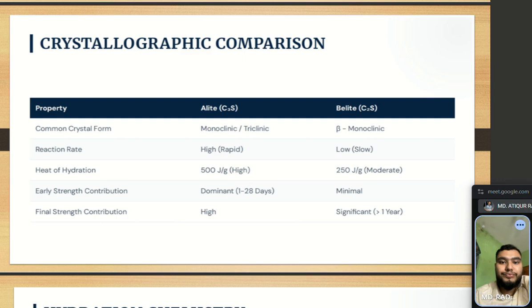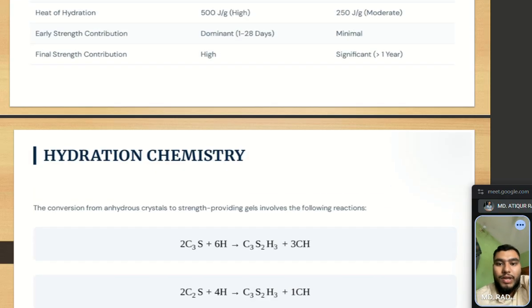Next slide. Crystallography comparison. Property: common crystal form: alite monoclinic or triclinic, belite monoclinic. Property: reaction rate: alite high and belite low. Property: heat of hydration: alite 500 and belite 250. Property: early strength contribution: alite dominant and belite minimal. Final strength contribution: alite high and belite significant.